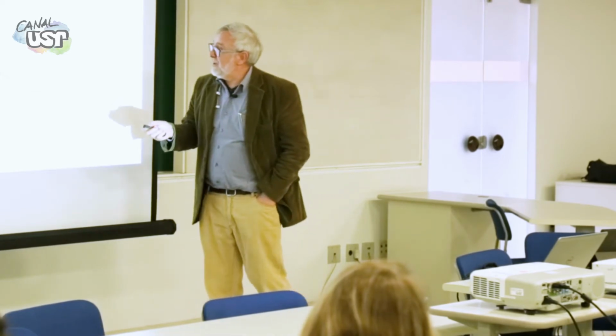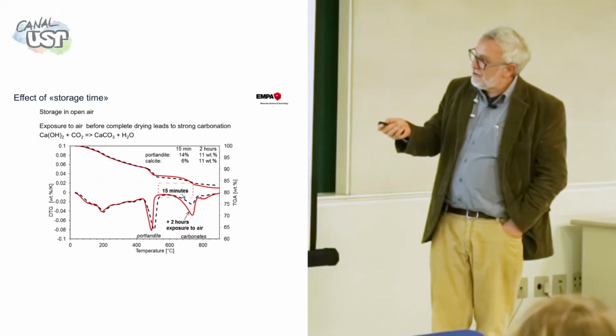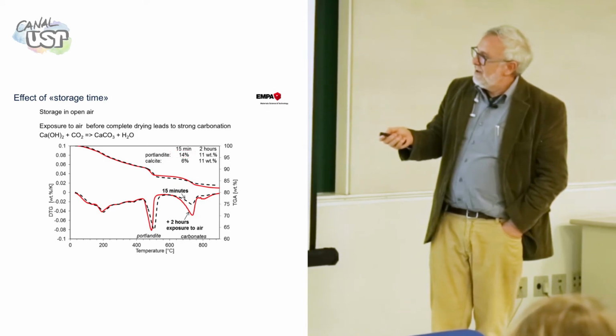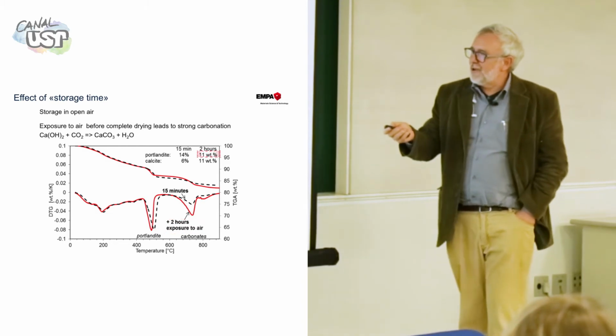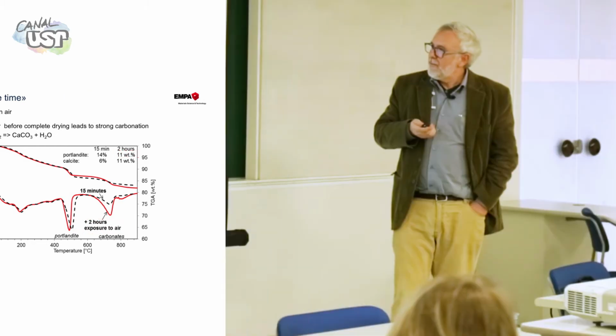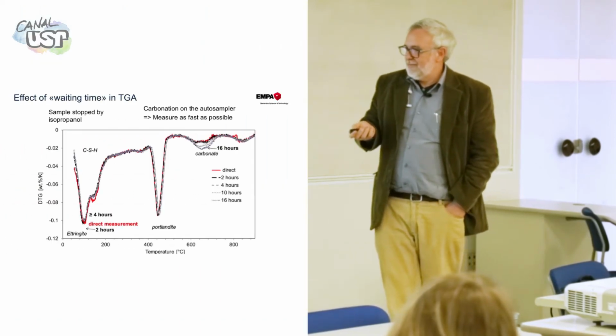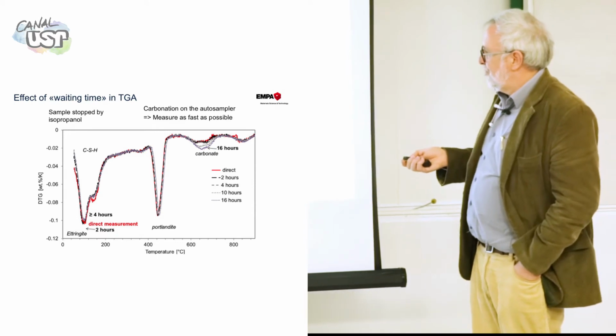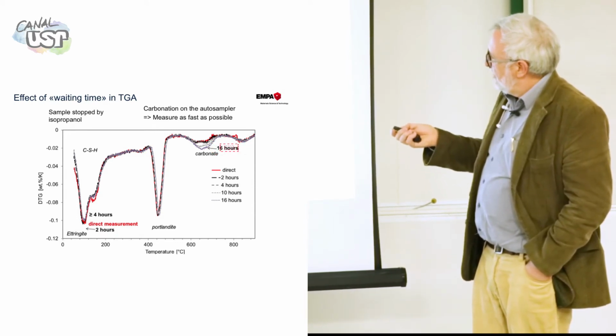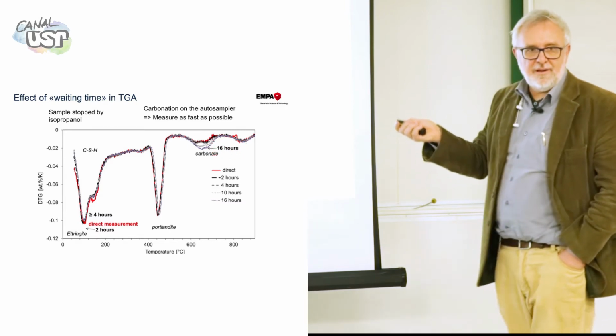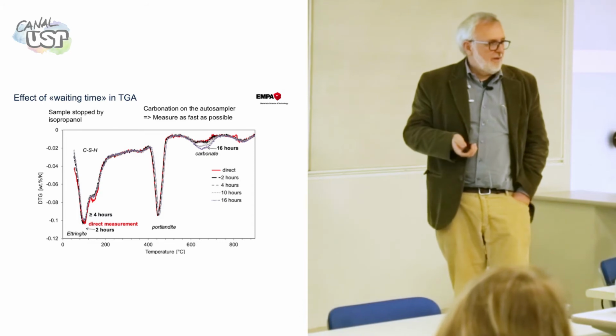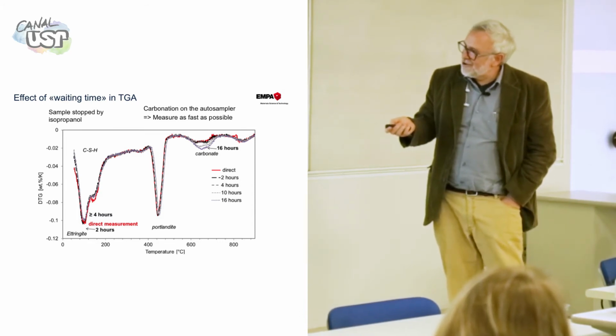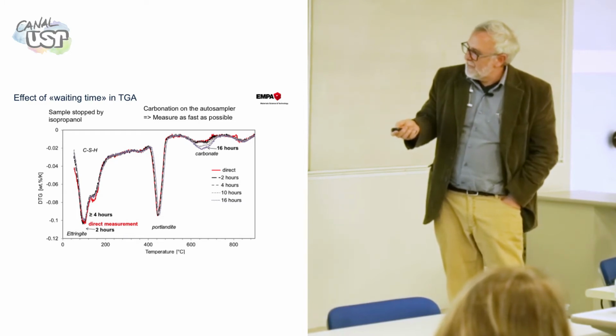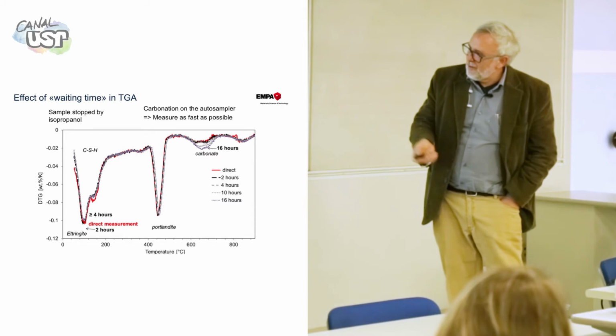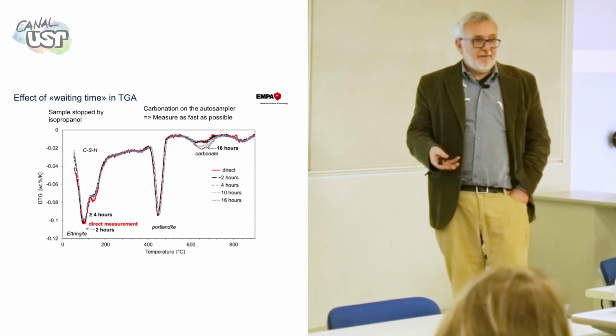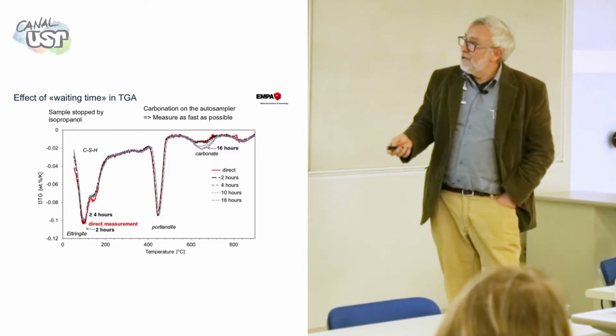The difference is in Portlandite: in 15 minutes, there's some loss, but not so much, 14% of Portlandite. Then in 2 hours, 11% of Portlandite. It's a huge change. Isopropanol, waiting time, same thing, and let's go to 16 hours. You see the carbonation peak increasing here. And Portlandite, you don't see much change, but you see carbonation changing, and you see here, in the composition, probably some ettringite carbonation. It carbonates very fast and loses a lot of water. So it's a huge influence.